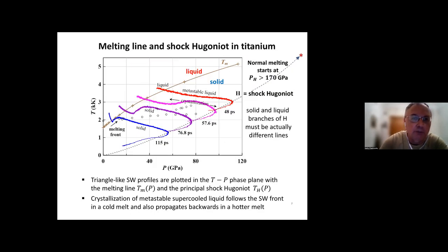Okay, it's interesting to plot the spatial profiles of the triangle-like shock wave in the TP phase plane, in order to demonstrate what states are formed behind the shock front. Here you see the melting line, which separates equilibrium liquid above the line and equilibrium solid state below it. The dashed line shows the position of the shock Hugoniot, and the shock front is located somewhere here. And you see the state here, as I already discussed, in liquid state. However, because it is located in the equilibrium solid part of this diagram, we should conclude that it's indeed a metastable liquid.